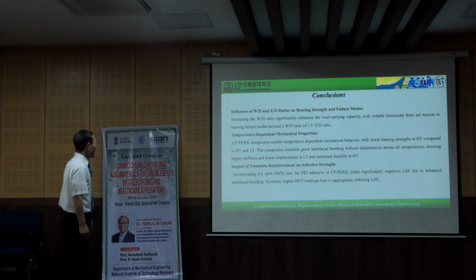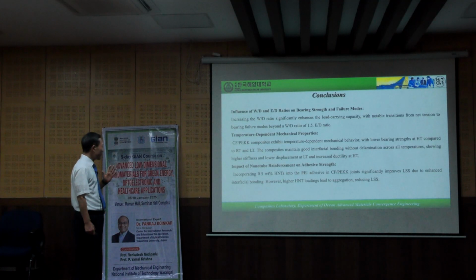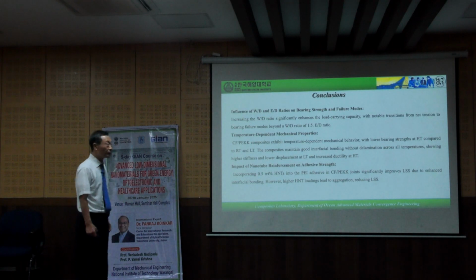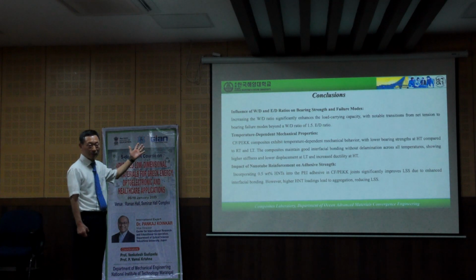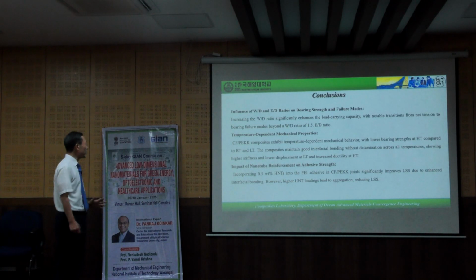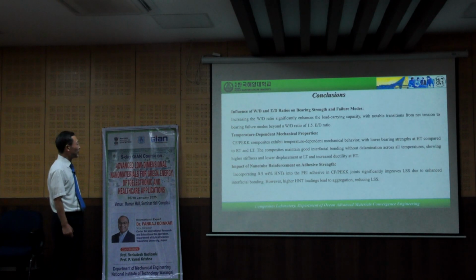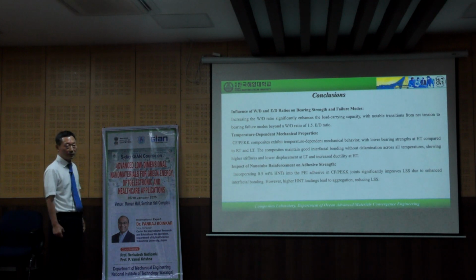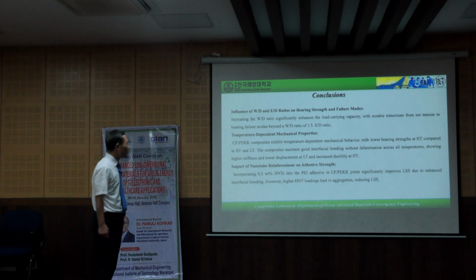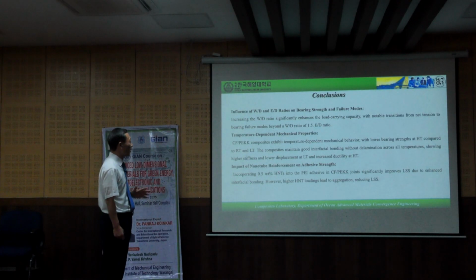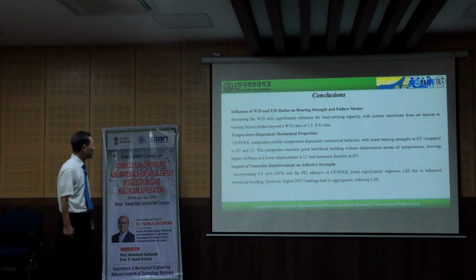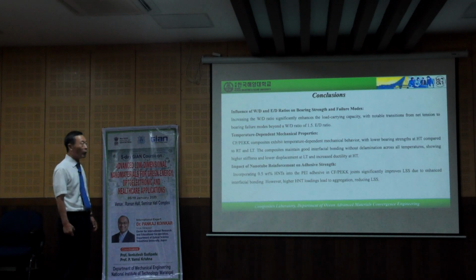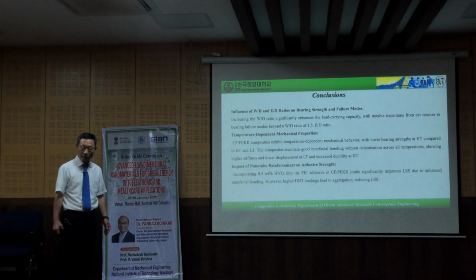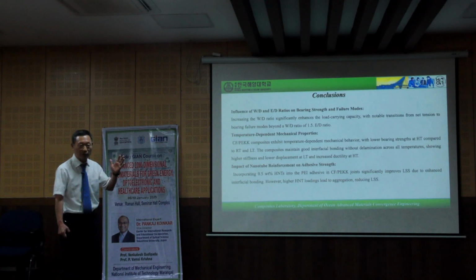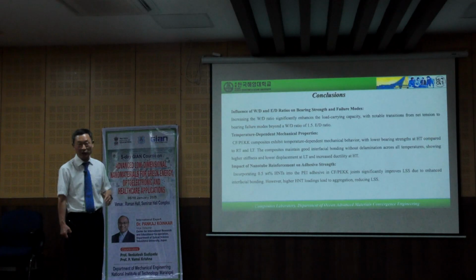The first, influence of W/D ratio and E/D ratios on bearing strength and failure mode. Geometry effect. Increasing the W/D ratio significantly enhances the load carrying capacity, with a notable transition from net tension to bearing failure mode beyond the W/D ratio of 1.5 E/D ratio. This is a very important thing regarding geometry effect.